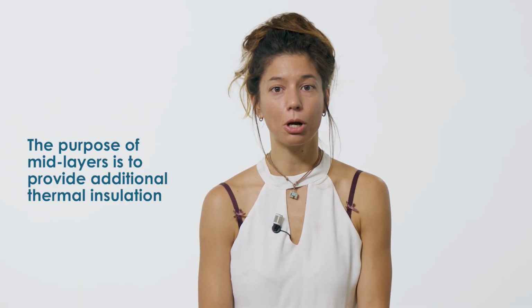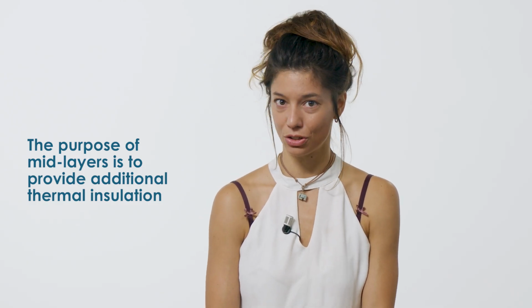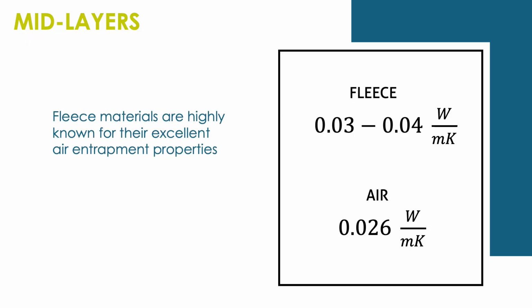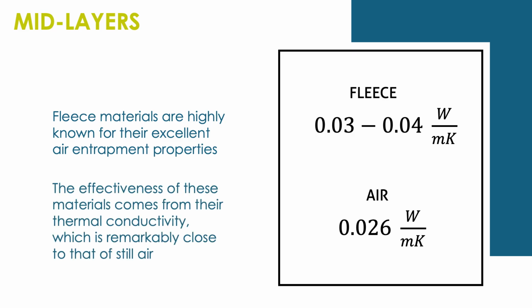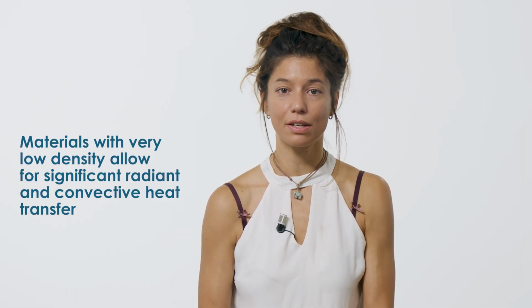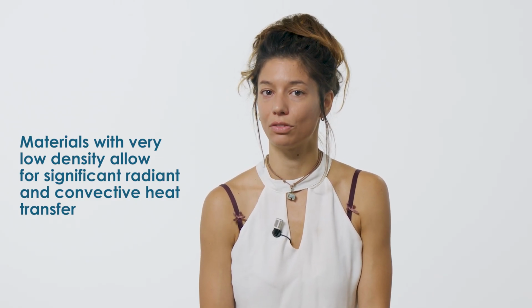Moving beyond the base layer, the purpose of the mid-layer is to provide additional thermal insulation. Modern mid-layers are frequently crafted from fleece materials, well known for their excellent air entrapment properties. The effectiveness of these materials comes from their thermal conductivity, which is remarkably close to that of still air. Typically 0.03 or 0.04 watt per meter Kelvin for fleece compared to 0.026 watt per meter Kelvin for air. While conduction is the dominant heat transfer mechanism, it is important to consider exceptions. Materials with very low density, such as spacer fabrics, allow for significant radiant and convective heat transfer. This means that a spacer fabric mid-layer contributes more to overall insulation in a non-convective environment, but its contribution is the lowest under forced convective conditions.